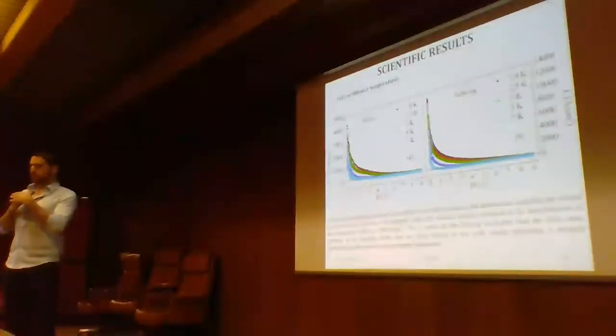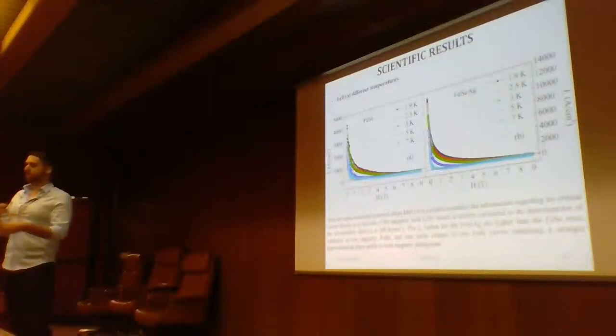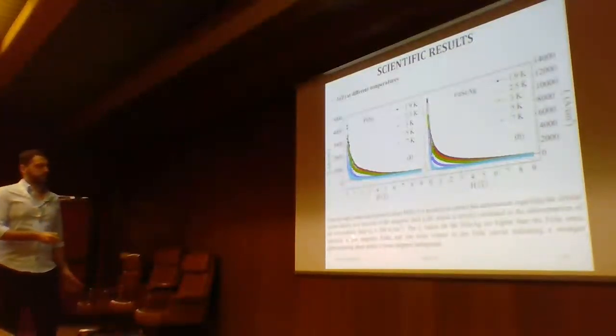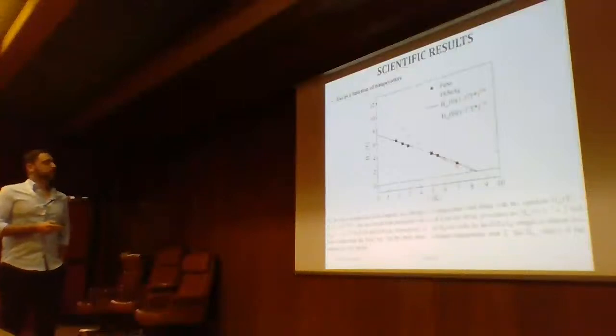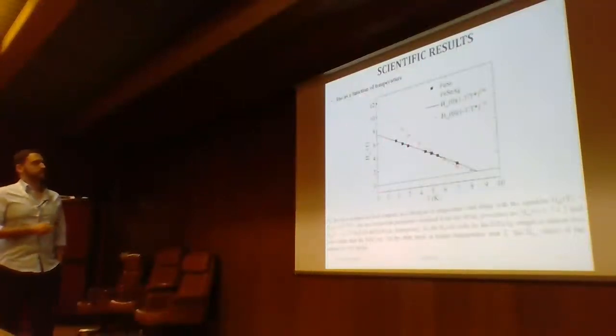So for applications, it's very important to keep your magnetic field below this irreversibility field. Otherwise, your vortices move around in the sample and also dissipate energy, and this is to be avoided for applications in general. So these characteristics can be very important. In particular, we have extracted from these curves this picture that characterizes the irreversibility field as a function of temperature for the two samples.